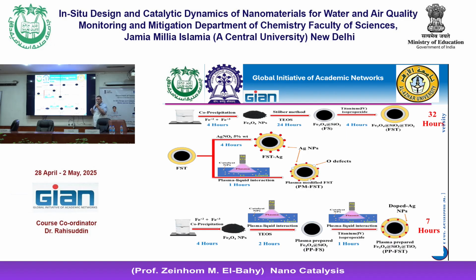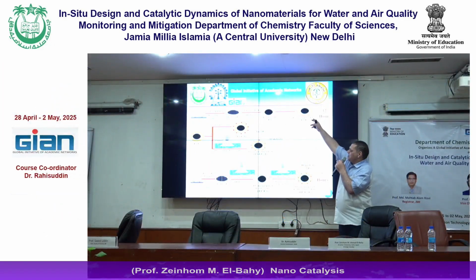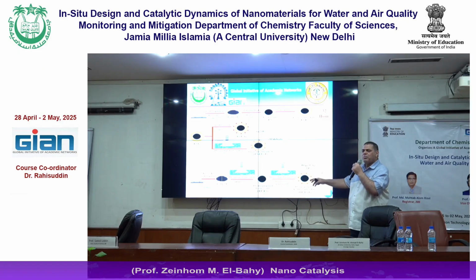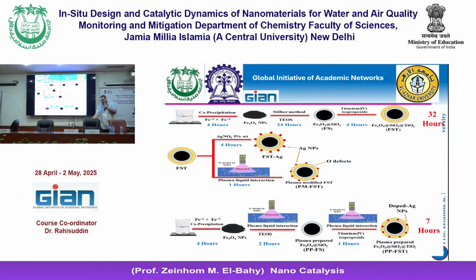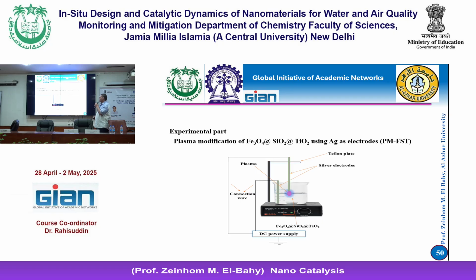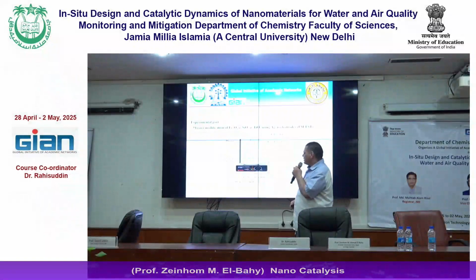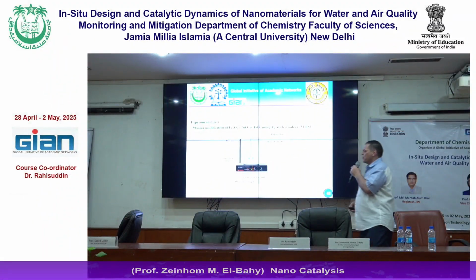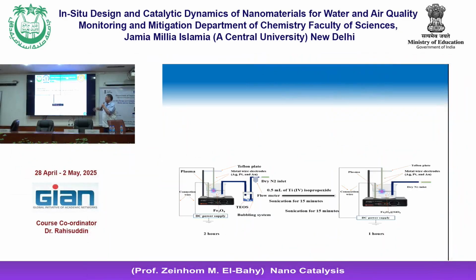What is the difference, Professor, between doing this reaction here and doing it here? Because if I can do it with the conventional method without an additional technique, what is the benefit of using plasma, if we can make it like this, and the plasma will be expensive? Because of this factor. Here you can do it in 32 hours. Here you can do it in 7 hours. This is the first factor. Second, when we measure the catalytic activity of this material and this material, it is completely different. This material has much more catalytic activity in the desired reaction.